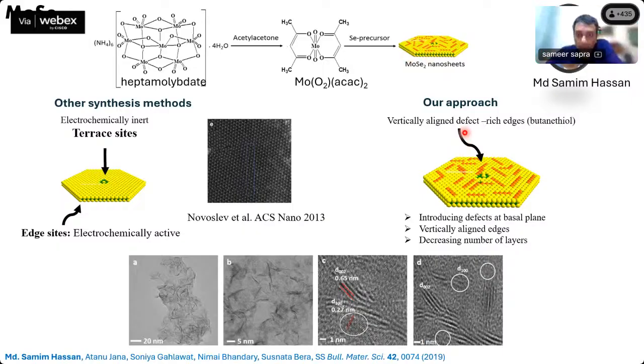You get these defects, which are absences of selenium, and because of that the molybdenum tries to attract the next nearest neighbor selenium and therefore folds, kind of crumples like a sheet. All of these 0.65 nanometer distances are typically the interlayer spacing. So what you see is that you have a lot of defects in this material, and you're not very happy with the defects.